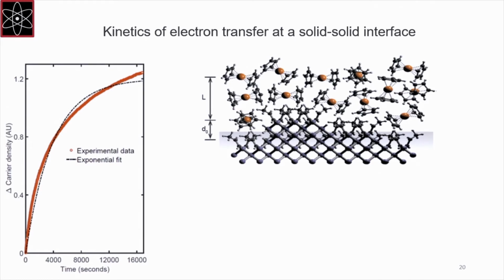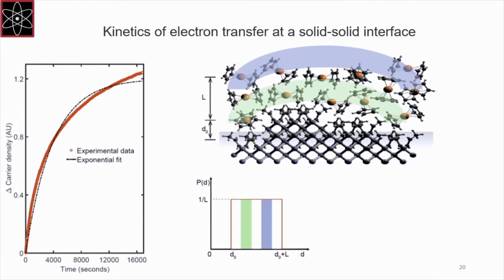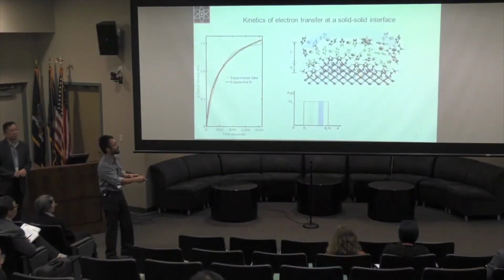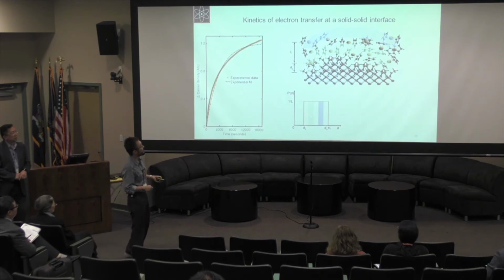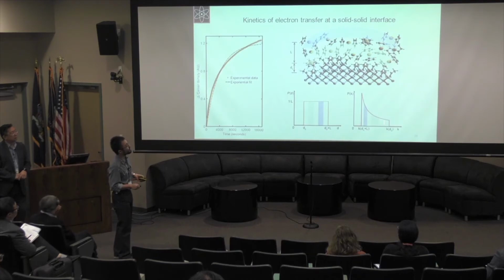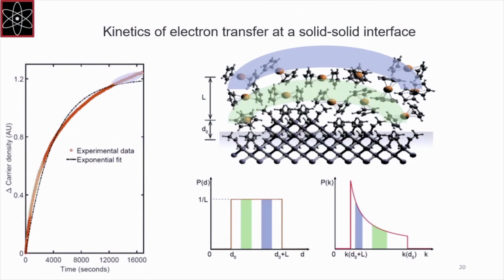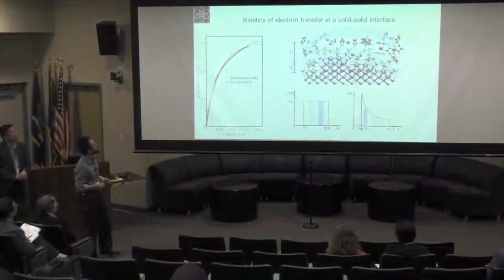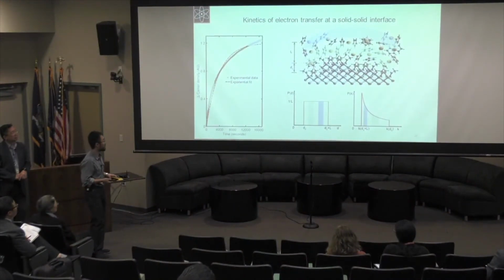And if we think about what's happening at the surface, the sensor surface is going to be rough. And there will be distributions of distance between the dopant and the core. So to first approximation, let's say that the probability density for finding the dopant is like some constant function that starts from some value d naught, that's how close the thing can approach, to some final d naught plus L. That's the thickness of the dopant layer that you put. Then you will have some populations that are closer that react with a higher rate, and populations that are further that react with a slower rate. And over here, the faster population and slower population would be represented by those deviations from the simple exponential model.